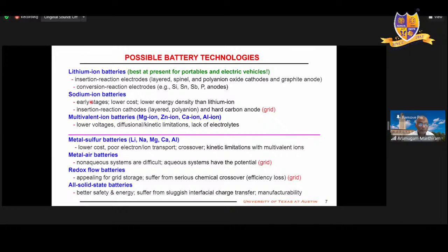these ions we saw earlier, when you use them, they have to move through the lattice. It's a crystal, right? You have material through which the ion have to move. Lithium and sodium monovalent, one charge they can easily move. When you have 2 or 3 plus charges, they will have a lot of electrostatic repulsion. With the manganese 4 plus or cobalt 3 plus, they will have a hard time to diffuse. So they will have poor ionic conductivity. And also there is no good electrolyte right now. So almost, as far as I am concerned, these are not going to be very useful as far as the practical batteries are concerned at the moment.